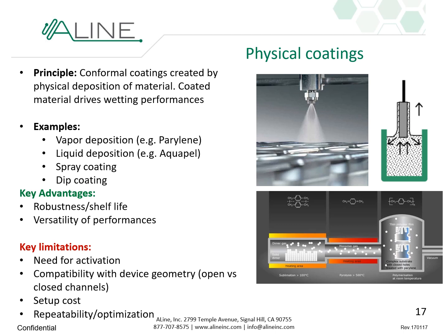You're probably familiar with parylene coating to increase hydrophobicity of microfluidic devices. You can have liquid deposition, like Aquapel is a pretty common process. It's a rain repellent for windshields that is also being used in microfluidics pretty extensively to induce hydrophobicity. You can also do spray coating or dip coating or different methods.